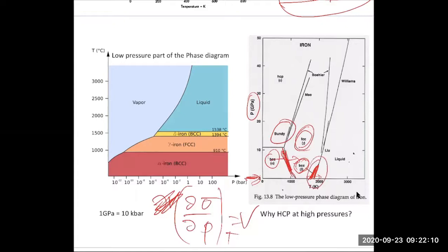And then at high temperature, sort of high pressure, at some point, there is no less close-packed phase anymore. You only have the two close-packed phases, HCP and FCC. So HCP iron is an oddity, right? It's kind of hard to make HCP iron under normal conditions, but it has been seen as precipitates in a matrix. So if you take an alloy and you precipitate out iron and you precipitate it out coherently, which is the early stage of precipitation, you sometimes see HCP iron, which for a long time people thought was a mistake. It couldn't be. But it makes sense, right?